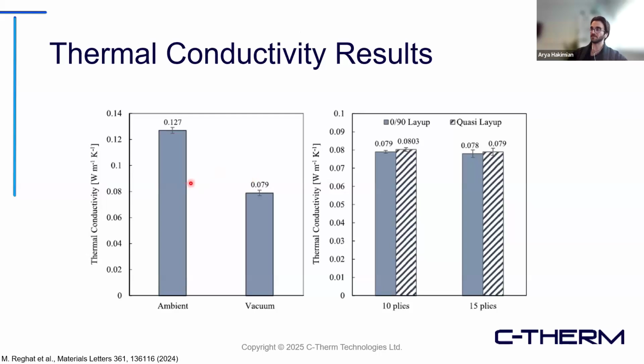I believe they had it set up in a vacuum chamber, but they were doing testing of the materials under ambient and then under vacuum conditions. As we can see, that's a quite notable difference in the effective thermal conductivity. So interestingly, these types of conditions can be as simple as just adding a little water, or putting it in a vacuum, or under different atmospheric conditions.